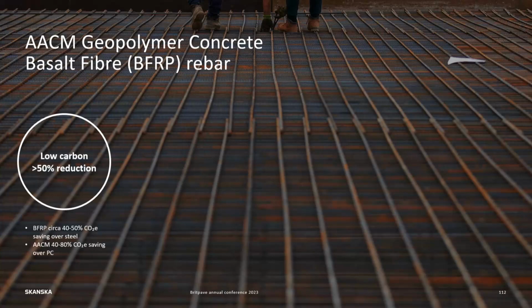So, moving a little bit into the area of the basalt combined with the AACM, what kind of CO2 reduction do you think is achievable through the combination of the two? Well, overall, the conservative figure would be a saving of about 50% CO2. The trouble is nailing down the baseline product that you're comparing to. So when did you last use or perhaps specify a CEM 1 concrete mix? We've heard the comparisons to CEM 1 a fair bit today, but I don't remember the last time a straight CEM 1 mix was used.